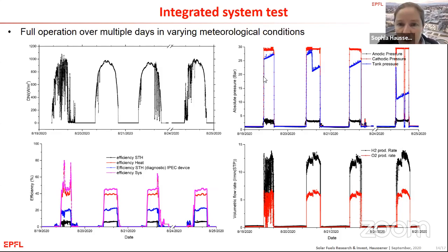You can see here on the right upper side, pressure in the system, particularly the blue one is the pressure in our storage tank, where you can see throughout the day we're filling the storage tank with hydrogen, and you can see this increasing the pressure, and then at some point we have used a little bit of the hydrogen, and this is where this drop comes. You can see on the lower right side production rates, hydrogen to oxygen. They have the nice 2-to-1 stoichiometry, but you can also see that the rates are correlated to the irradiation conditions. So if you have choppy irradiation, you have choppy production rates.